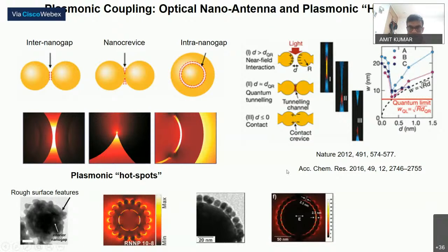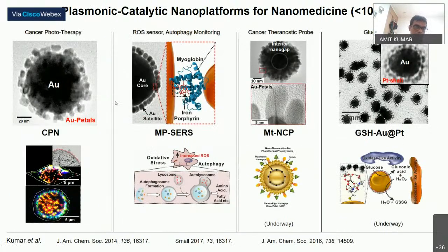Using this knowledge, in my postdoctoral research I created many nanostructures, for example this kind of core-petal nanostructure. If you modify simple shapes, for example spheres, with this kind of surface branches, we call them nano antennas. They show very enhanced optical absorption as well as scattering.